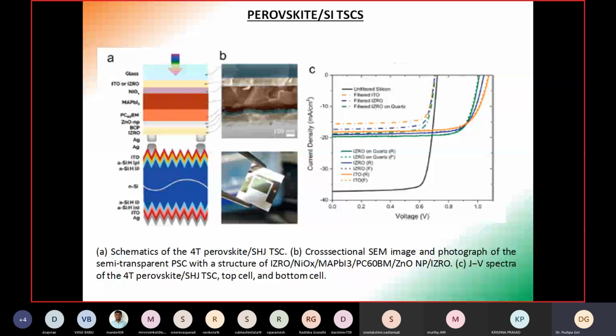So the highest efficiency for this perovskite silicon solar cell was 13%, and when we reached 2020, it had increased up to 29-30%. So exceeding the record efficiency for silicon, normally 25 to 26%, and perovskite individually was about 25%. Both were having nearby 25-26%. But when we combined both, perovskite on the top and silicon on the bottom, what happened? Our efficiency increased up to 29.1%.